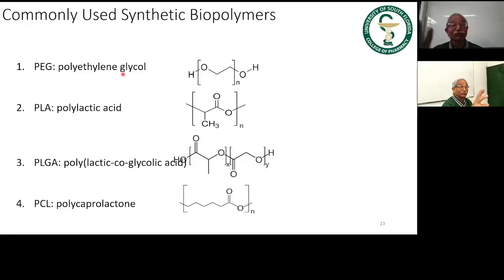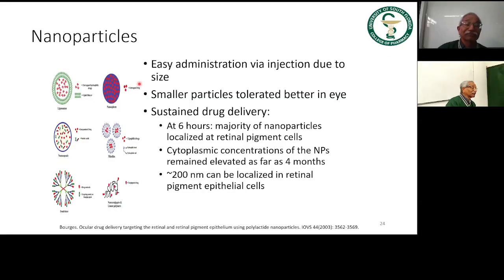If you exclusively use polycaprolactone, then the depot will sit in your eye but not release anything because no channels are created. But if you use polyethylene glycol, PEG, which is hydrophilic, gradually the PEG will dissolve and create channels. They are macro channels, and the drug will start coming out of the polycaprolactone. As the concentration gradient is created, the drug will always travel from high concentration to low concentration. Your depot will have high concentration, it will go to low concentration, so it will be released out. That is how combinations of polymers are utilized.